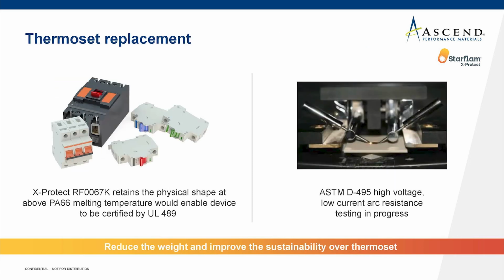Another application space is in the production of enclosures for circuit breakers. Especially in North America, these enclosures are primarily produced in thermoset. With X-Protect technology, we can produce those housings and perform really well in what they call the high voltage, low current arc resistance according to ASTM, which is shown in the right-hand side picture. It's a bit comparable to CTI, only the voltage is higher and you don't need any electrolyte to run the test. This is due to the fact that when switching those circuit breakers, you might generate an arc in the switching chamber. And of course, that arc should not lead to any harm of the enclosure or compromise even the function of the enclosure.